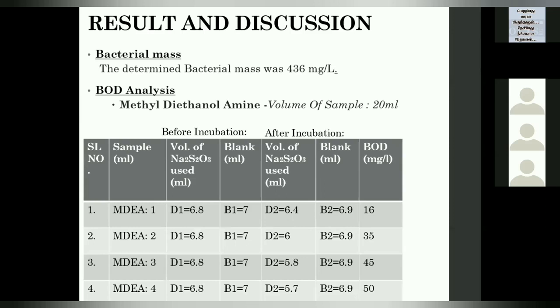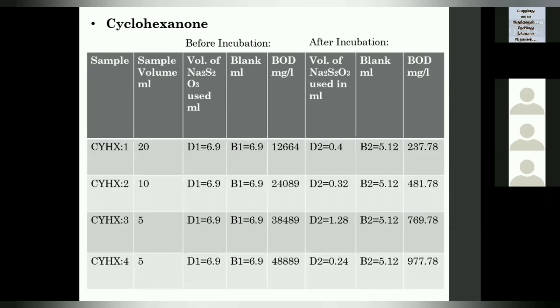So determination of bacterial mass was done by the normal method of weighing it without the crucible, and then with the bacterial mass plus the crucible. Then this was the result we obtained for BOD analysis. You can see the BOD values here. And this was for cyclohexanone. This was for MDEA, while this is for cyclohexanone. We noted the BOD levels before and after incubation. You can find the BOD level is considerably reduced after incubation with the effluent treated bacterial species.